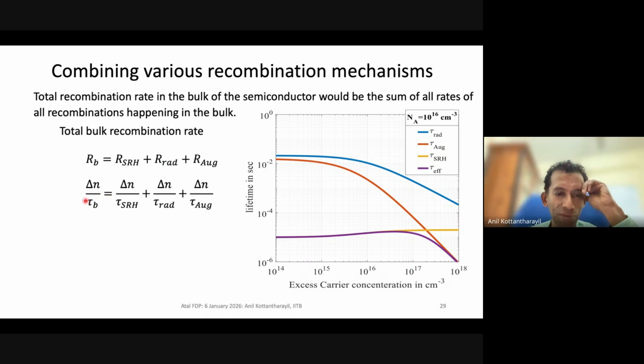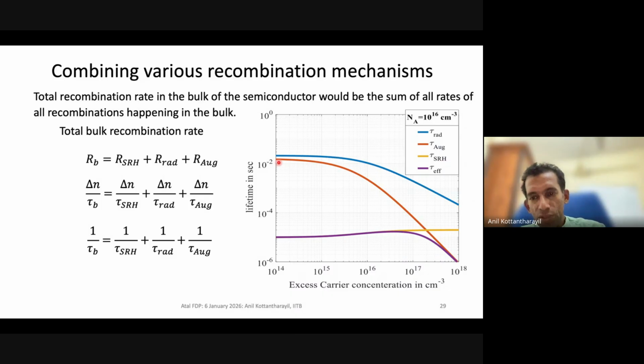You have what is called an effective bulk recombination lifetime, and that is given by this equation. So delta n is common on the left-hand side and the right-hand side of this equation, so you can eliminate that. So the effective lifetime is given by this equation, right? And you can see the plot of this. This is the radiative recombination lifetime, this is the Auger recombination lifetime, and this is the Shockley-Read-Hall recombination lifetime. And the effective lifetime, for semiconductor silicon especially, is most of the time decided by the SRH recombination, which means the concentration of the defects in the semiconductor. For silicon, yeah.